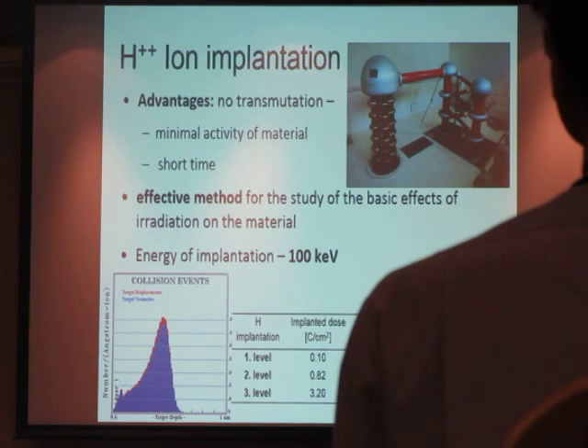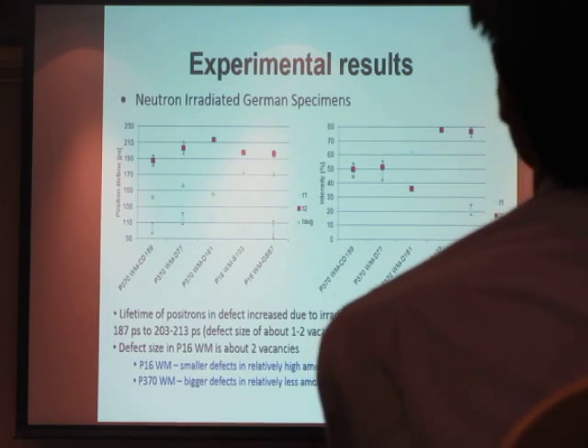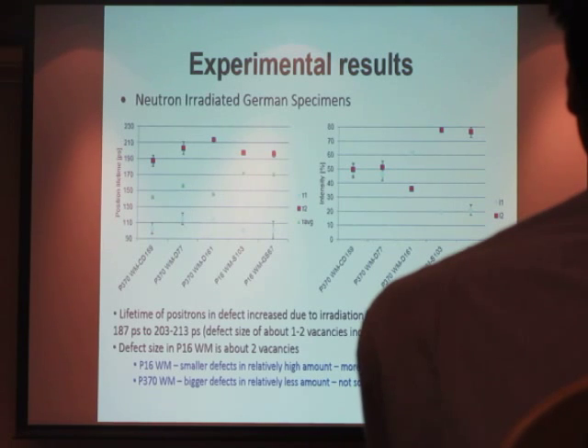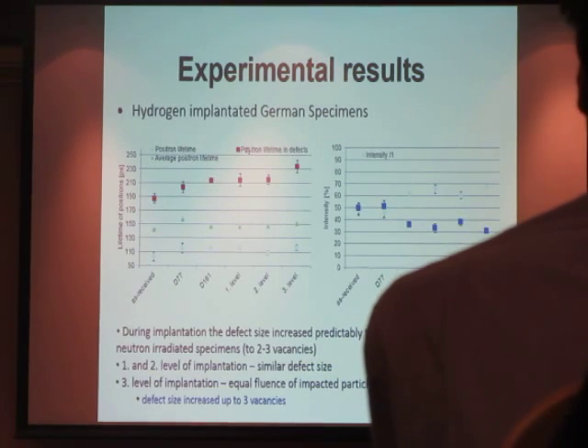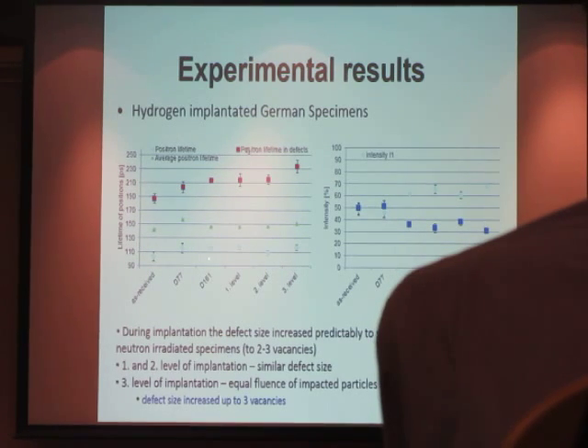Also, VVER reactors in 60 years will never achieve 2 dpa. And when we compare these results, not irradiated and implanted, there is as received, irradiated, and 3 different levels of implanted. One material is P370, and we see a comparable level if we irradiate and implant to 2 dpa. The defects are almost the same, so it's proved that defects caused by implantation are very similar to the original irradiated defects.